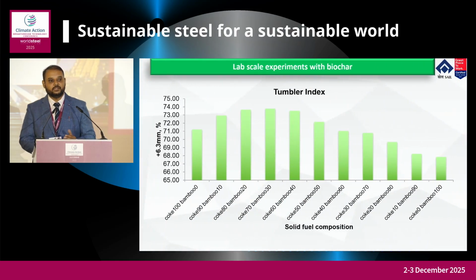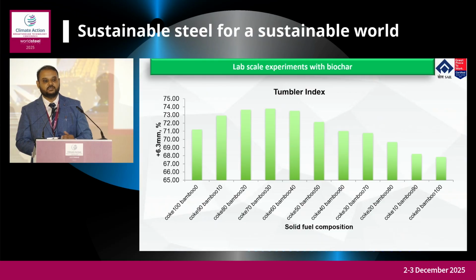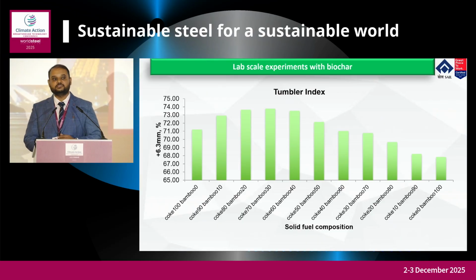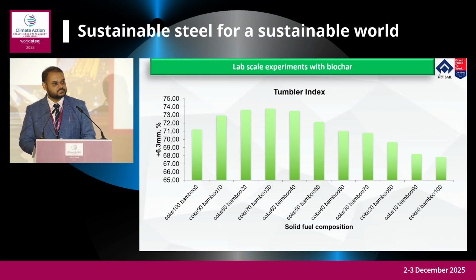Next, coming to the tumbler index, which is the measurement of strength in sinter for actual blast furnace condition. The higher, the better. The plateau comes at around 20 to 40% range, beyond which it deteriorates to a very large extent and is not recommended with a conventional process. However, there are other processes currently under development so that we can utilize more biochar.